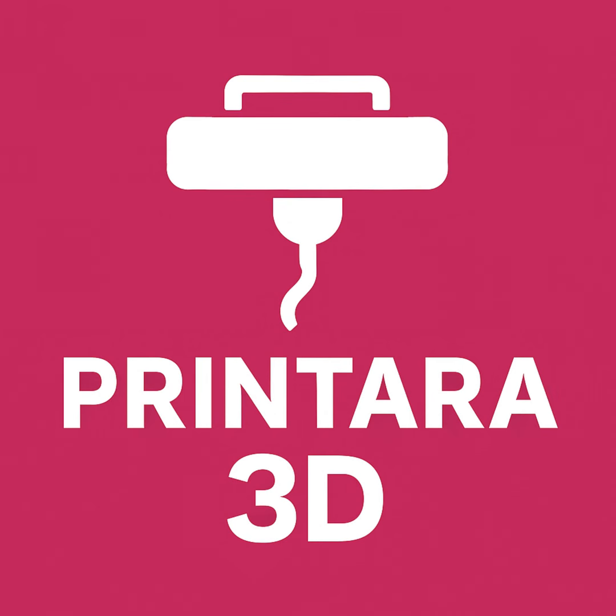Gotcha. And the final weakness, the enemy of pretty much all filaments, moisture, hygroscopic. Yep. PLA loves to absorb moisture from the air. It's hygroscopic. And damp PLA is bad news for printing. You'll hear cracking or popping sounds from the nozzle as the water instantly turns to steam. What does that do to the print? Causes all sorts of problems. Visible bubbles or voids in the print, really poor layer adhesion, meaning a part is weak, and lots more stringing. Those annoying little threads between separate parts of the print.